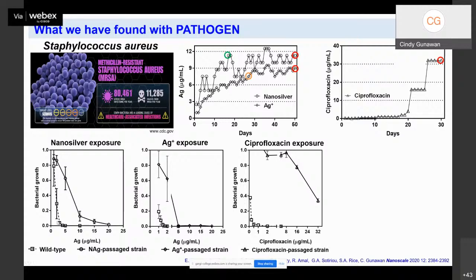So what happened with this MIC with the bacteria that has been previously pre-exposed to nanosilver? We could see that the MIC of the pre-exposed bacterial population has increased to 15 to 20 micrograms per mil. So it means that there is a 5 to 7-fold increase in the MIC of nanosilver on the Staph aureus, which confirms the development of a stable resistance trait.